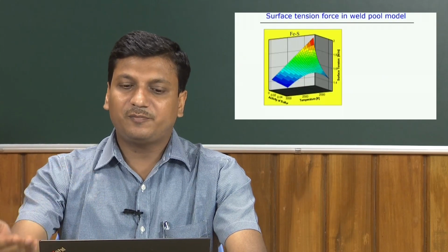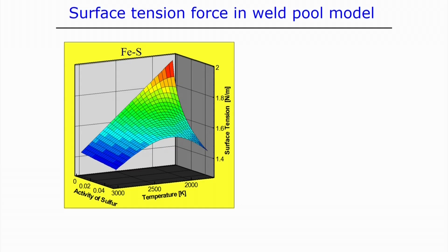So, we can further analyze the surface tension force effect of these surface active elements in the weld pool model. Here we see one binary system, that means Fe-S, pure iron and sulfur. So, sulfur also can act as a surface active element. Here we can see a combined effect in a three dimensional figure, where the surface tension force is a function of the temperature as well as the activity of sulfur, that means the amount of sulfur. Temperature and sulfur both make a combined effect on the surface tension force. So, this figure shows the nature of the surface tension force.